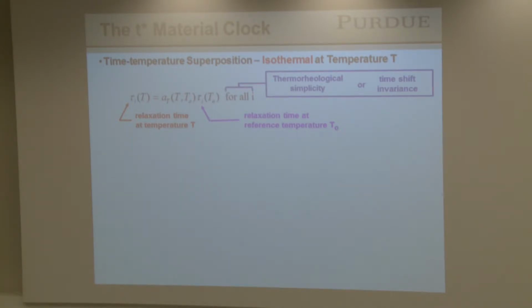Okay? And the assumption is that temperature causes all of the relaxation times to change the same way, and that's called thermorheological simplicity, or another name is time shift invariance for that material. So what it says is that material property that we had in the previous slide, the relaxation function, which we said is a sum of exponentials. What we now do is instead of having it over just tau, it's A sub T times tau, because that's the relaxation that occurs at temperature T. Now, we do a little trick at this point. What we say is, okay, I can rearrange this.